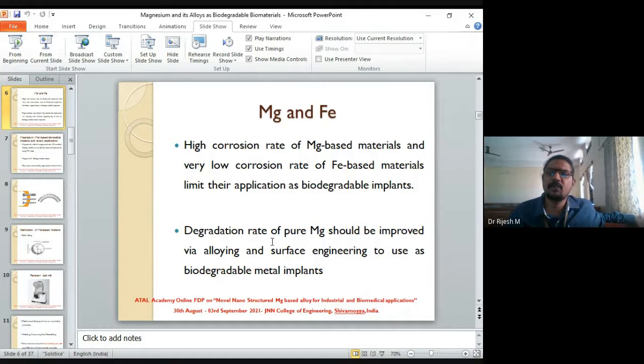The degradation rate of pure magnesium should be improved, and this is generally done by alloying and surface engineering to use it as a biodegradable metal implant. Correct. You can do one of two things: alloy magnesium with some alloying additions and reduce the corrosion rate, or coat magnesium with some materials where the magnesium degradation is reduced. So this is where the challenge lies. This is where the engineering of these two things lies.